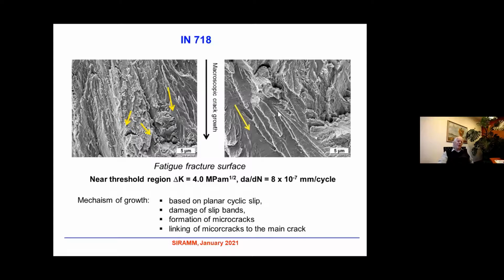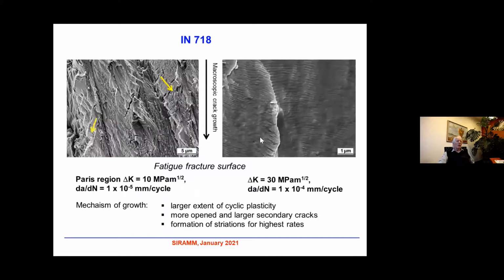As regards the fatigue fracture surface, for the near threshold region, where delta K is only 4 and the crack growth rate is low, we can see on the fracture surface that the mechanism of growth in this case is based on planar cyclic slip. Damage takes place mainly in slip bands. It is derived from other observations of the microstructure of this material. I am not showing this data here. And we can observe formation of microcracks and linking of microcracks to the main crack. It is the mechanism of crack growth in this material at low crack growth rates.